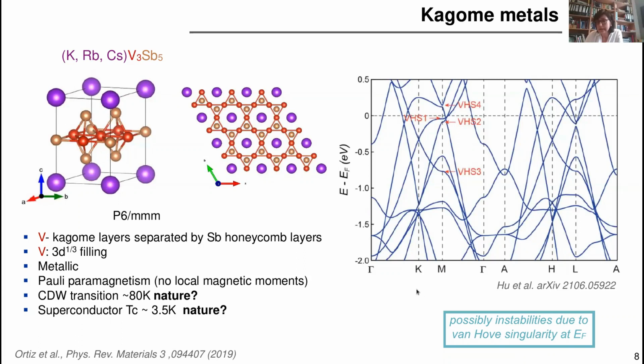Now if we look at the band structure, which is extremely useful for these systems, we see that we have these vanadium atoms with 3 orbitals: dxy, dxz, dyz. What we observe is that the filling of these systems is very near Van Hove singularities. So we could think that the appearance of this charge density wave has something to do with the filling being very near this Van Hove singularity, which brings a large instability into the system, and the system wants to move away from this unstable behavior.